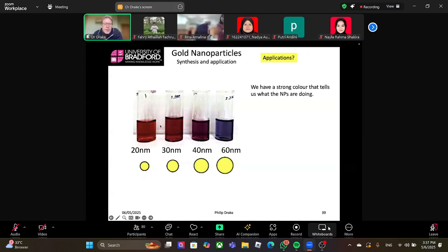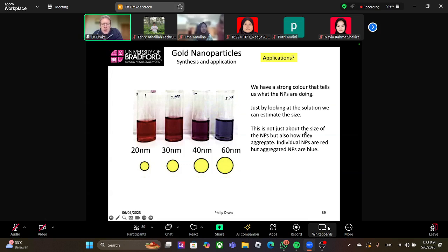There's a strong color dependence, and this is what makes gold nanoparticles very interesting, the color change from red to blue. Just by looking at the solution, you can estimate the size. So your eyes can become sensors to work out the size of nanoparticles just by looking at the color of solutions. But it's not just the size of nanoparticles, it's how they're aggregated. So if the nanoparticles are touching, they become blue. If they're individual particles, they stay red.